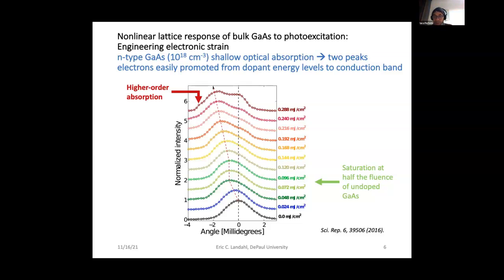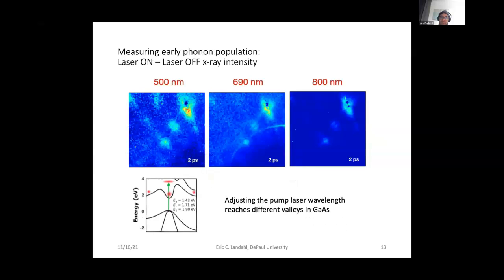I do have a question. Maybe you partially answered that already. If you excite at a different pump frequency, you do see different effects, right? Different in the case of gallium arsenide, that's correct, for the diffuse scattering. Is that due to the fact that you are below or above the valleys of gallium arsenide, or is something different playing a role? If you are below the valleys and only exciting near gamma, I guess the Froelich coupling is the dominating one, so zone edge polar phonons, zone center polar phonons. And if you excite into the valley, I guess you get more phonons involved. But this is what I would guess. Is this your interpretation of your results? That's my interpretation of this.